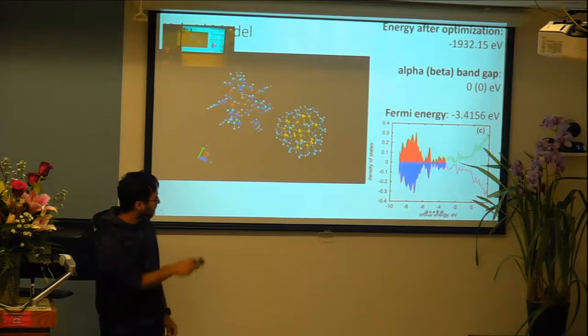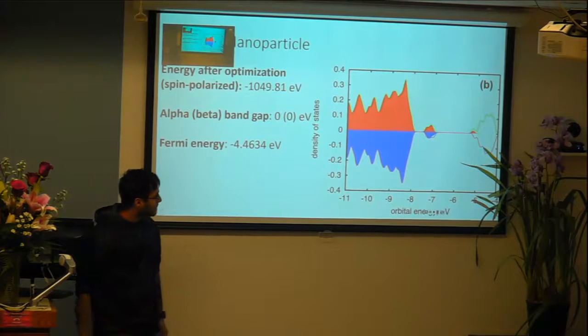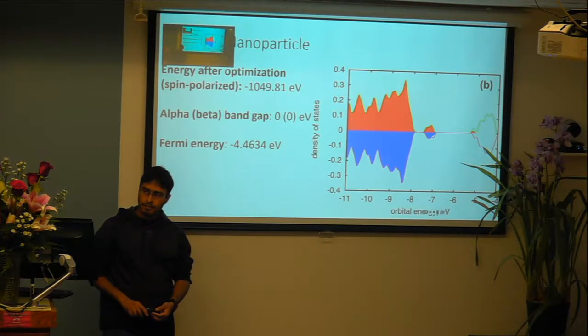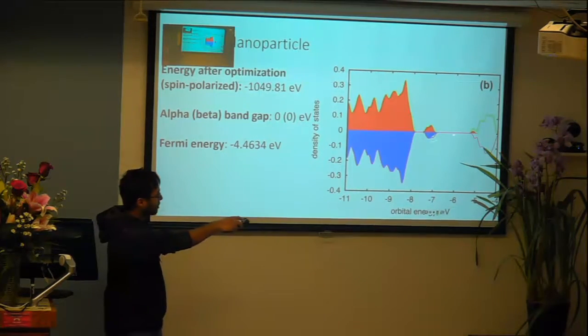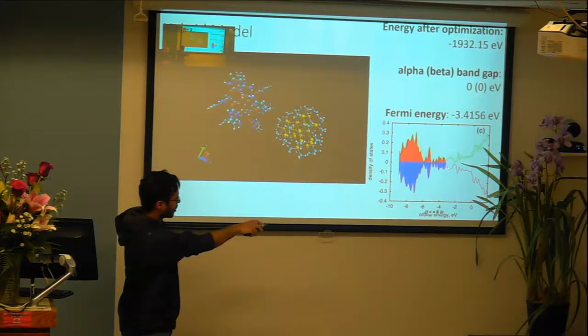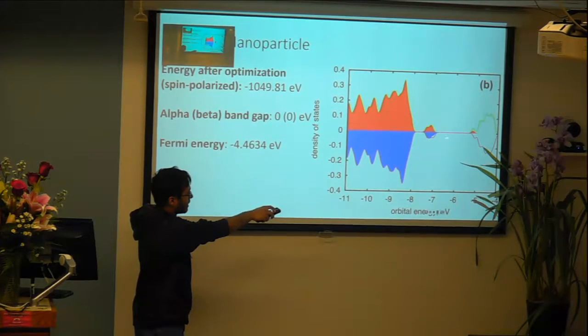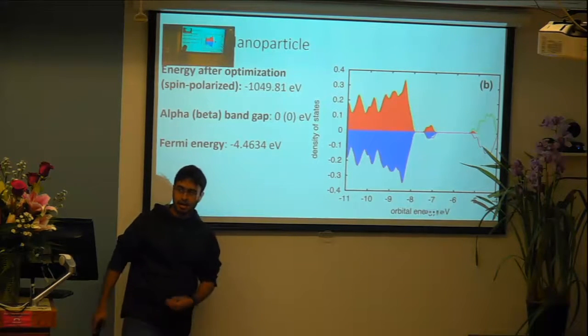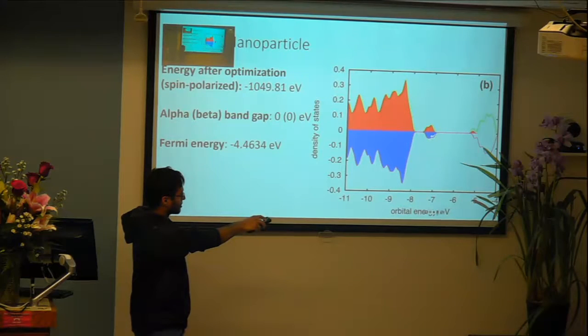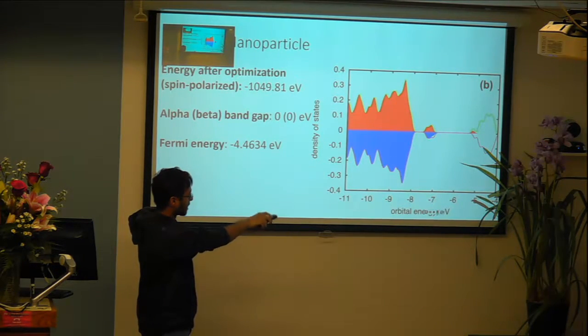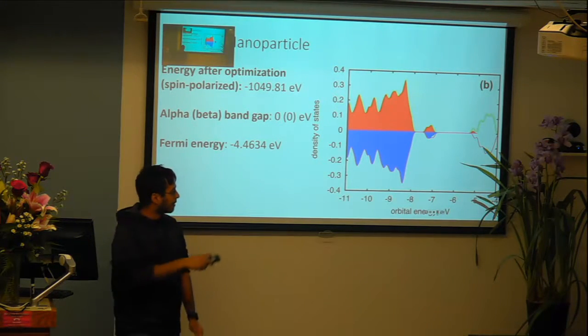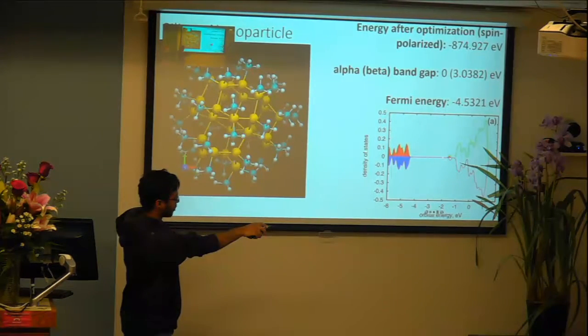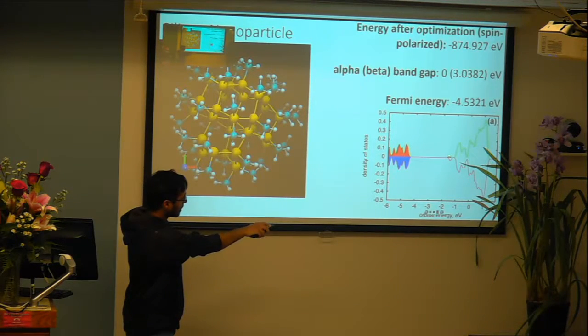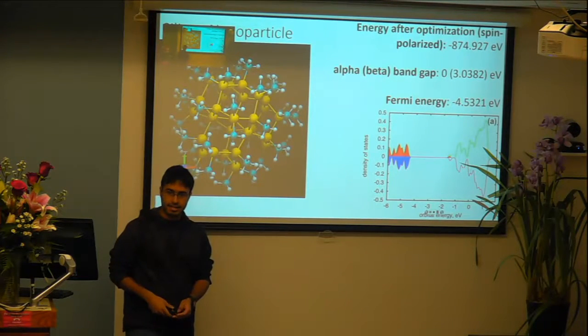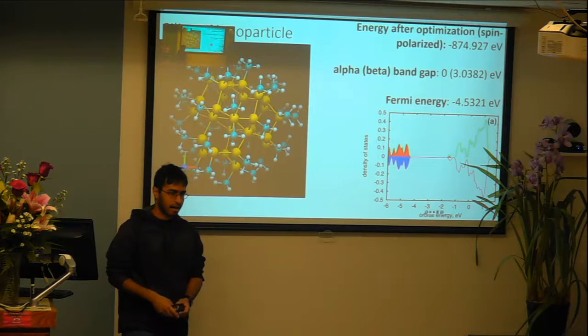Here we can see as well from this figure that HOMO and LUMO are very close to each other, so the band gap's essentially zero, and the same thing actually occurs right here. So you can see that this final state that is occupied is only partially occupied, and right next to it is an unoccupied state. And similarly, in the beta orbitals, there's a partially occupied state right here around negative 7.5 electron volts. And then finally, for the silicon nanoparticle by itself, again, there's a partially occupied state in the alpha orbital, and very close to it, you see that there's a completely unoccupied state. So those would cause the absorption spectra to have peaks at low energy.